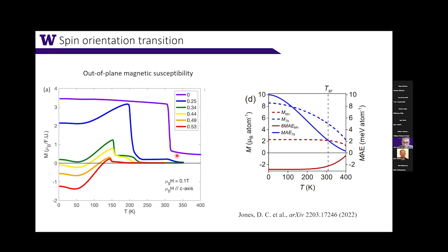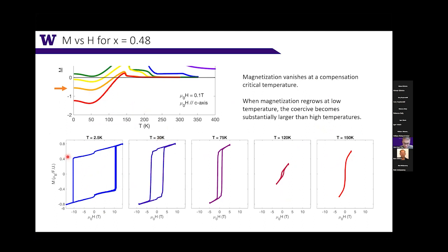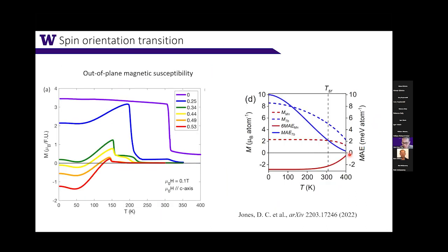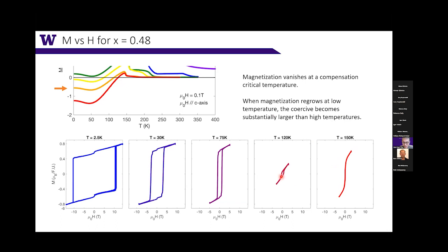Obviously this negative magnetization comes from the unusual asymmetry of temperature dependence between the terbium and manganese moments, where the manganese or chromium average moments saturate at a much higher temperature scale compared to the terbium moments. If you look at M versus H curves at different temperatures, at high temperature you have the usual ferromagnetic response. But at some temperature where the magnetization vanishes, you have total compensation. This is exactly the point where the terbium moments grow and become comparable to the manganese or chromium average magnetization, so the magnetization vanishes. But when the magnetization grows again, you have a much larger coercive field compared to the higher temperature where you have similar magnetization.